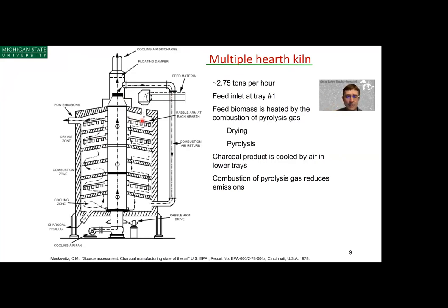As the central shaft rotates, the rabble arms push the biochar towards holes in these trays, allowing the material—biomass on the top tray, but eventually biochar—to be pushed to a lower tray. Your feedstock is successfully pushed to lower and lower trays, exposed to pyrolysis temperatures. Pyrolysis occurs, and by the time you get to the bottom, you can collect your biochar product, listed here as charcoal—though it would be biochar when you start with biomass.